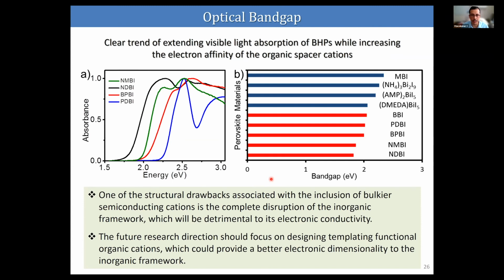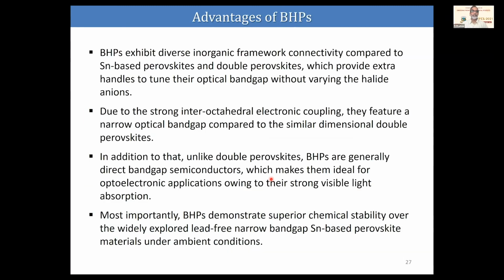And coming to the last 2-3 slides, I can summarize the advantages of the bismuth halide perovskite materials we developed and other materials developed by other groups compared to other lead-free perovskite. One is they exhibit a diverse inorganic framework connectivity compared to other lead-free materials like tin-based and double perovskite, which provide extra handles to tune the optical band gap without varying the halide anions.